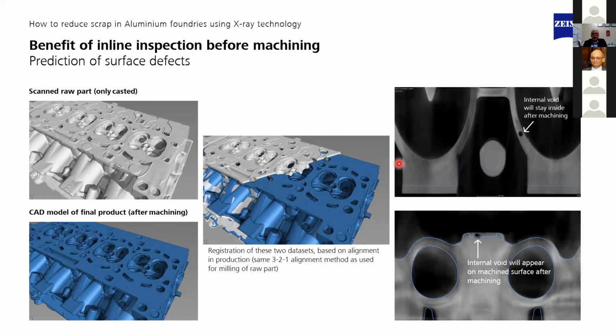So this is my machining profile. This defect is well within the machining profile. It means after the machining is done, the defect is still within the part, which means it will not create any kind of imbalance to the part. So I can still allow this part to go to the next phase, because I know very surely that even after the machining is done, this defect is not going to show up. So I can still use this part.